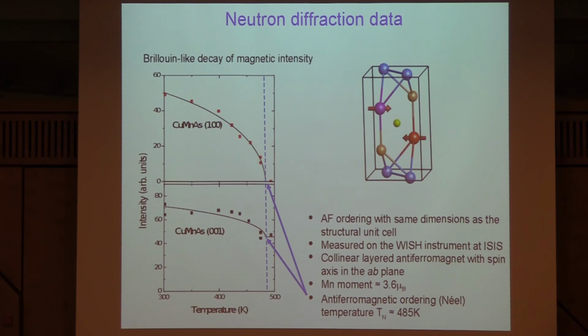And finally, some neutron diffraction data just to prove that it really is an antiferromagnet. Basically, this is the lovely Brillouin-like decay. This is the part of the signal that's only sensitive to magnetization, so of course it decays to 0, and here's a part which has some magnetic component and some structural component, and we can clearly say they decay at the same place, giving us a Néel temperature of 485 Kelvin. With manganese moment, for what it's worth, of 3.6 Bohr magnetons, and this was measured at ISIS. They should change the name of that. At ISIS in the UK.